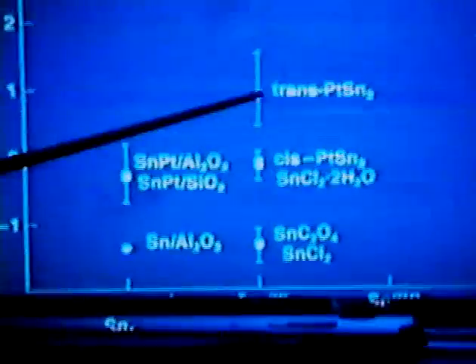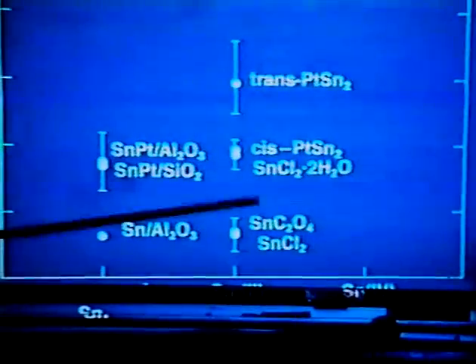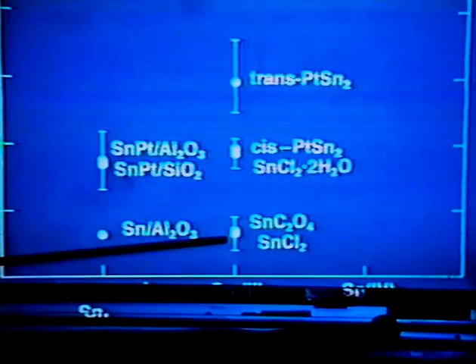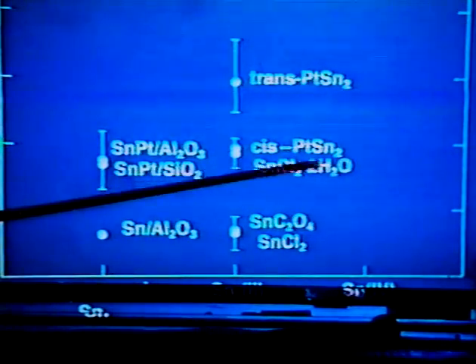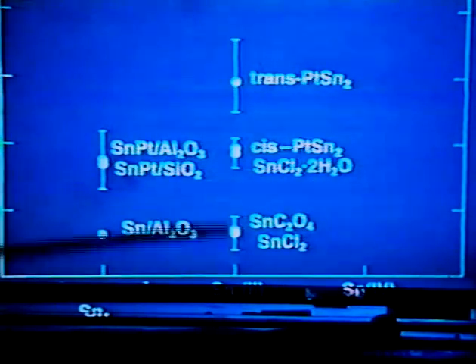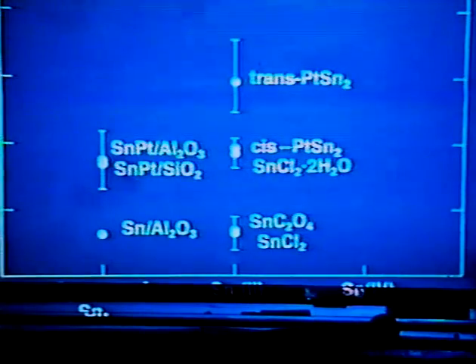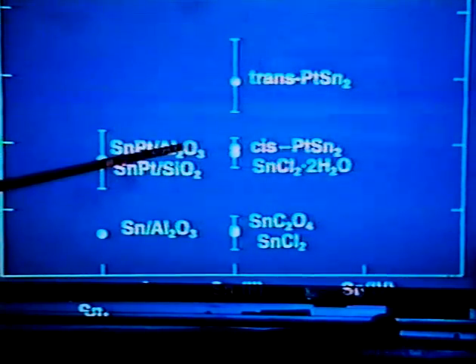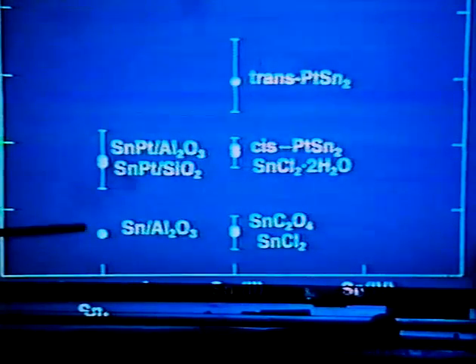Over here are some tin-4 compounds, SnCl4 and SnO2. They have a higher binding energy than tin in the foil, which is not unexpected. That's tin-4. In the middle, we've got some tin-2 compounds, PtSn2, a trans salt, cis salt, SnCl2, tin oxalate, SnCl2 hydrate. They're down around 0. It turns out we can't discriminate between tin-2 and tin metal. The binding energy doesn't change for one reason or another. And here we've got tin in various catalysts. Tin alumina, tin silica, tin platinum silica, and tin platinum alumina. These all have near 0 shift in binding energy.